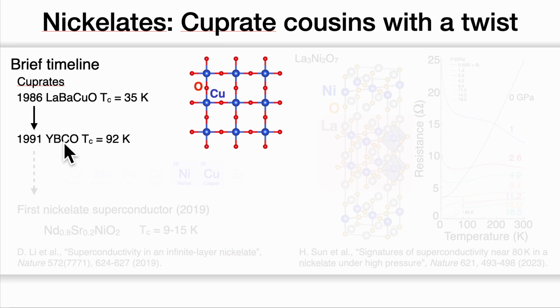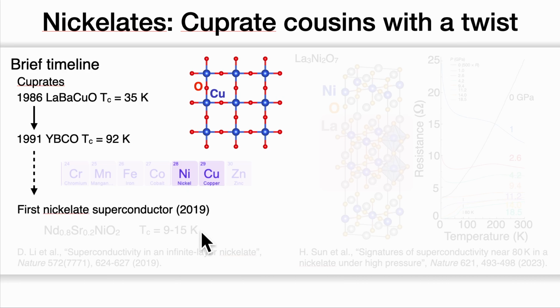Scientists wondered if materials other than cuprates also have high Tc. Nickel is one candidate because it is just next to copper in the periodic table. Due to the challenges of its many oxidation states and the material synthesis of nickelates, the first nickelate superconductor was discovered only recently, in 2019. This nickelate has a Tc around 9 to 15 Kelvin though.